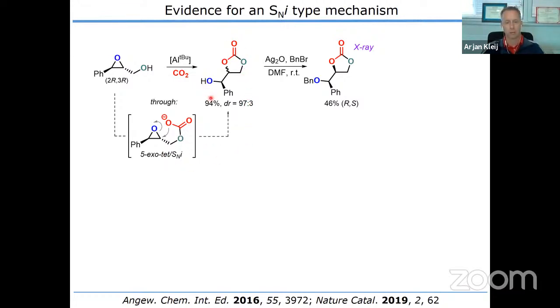However, we could not determine here the absolute configuration, so this product was not suitable, so we had to convert it into this benzoyl protected derivative, and this was now suitable for X-ray diffraction. And finally, we were able, by X-ray diffraction, to determine the absolute configuration. And what we saw is that we see inversion of configuration at this carbon center, and that is exactly what you would expect on the basis of this mechanistic proposal.